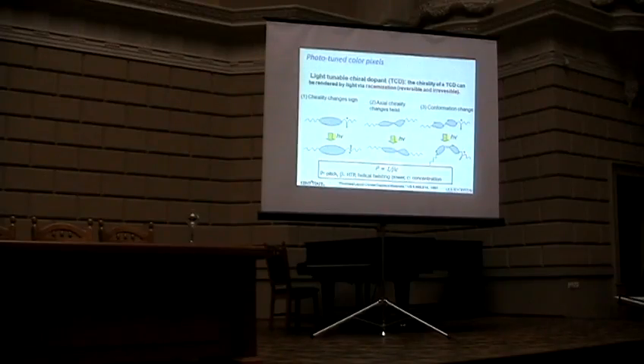On the other hand, you can use different kinds of molecules. They may rotate their chiral helical axis and change from clockwise to counterclockwise. The other is just a conformation change, and it is well known that people use azobenzene, which can change from trans to cis, or cis to trans. And in that case, the chirality actually is not changed.